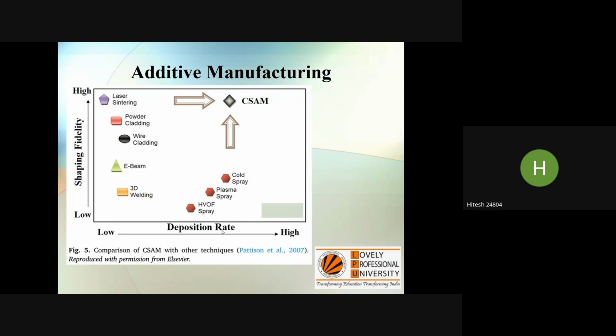And further, the deposition rate is very high in this case. Deposition rate means if you are feeding 1 kg of powder into the feeder, how much material is getting deposited on the surface? Let us say 500 grams. So that is called the deposition rate. Here the deposition rate is very high. That is why this process is preferred over the other processes like laser sintering, powder cladding, wire cladding, e-beam, 3D welding, and even thermal spray processes. These processes.